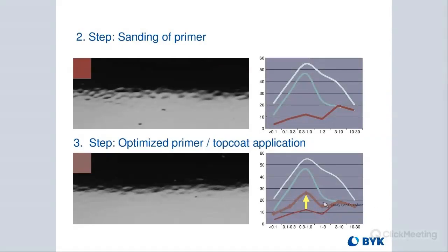Generally, we look at the WB and the WD values, and we want the WB to be somewhat higher than the WD. Very, very rough convention, we would say maybe a 3-to-2 ratio, but that is very dependent on the overall structure in the surface, what the exact ratio would be.